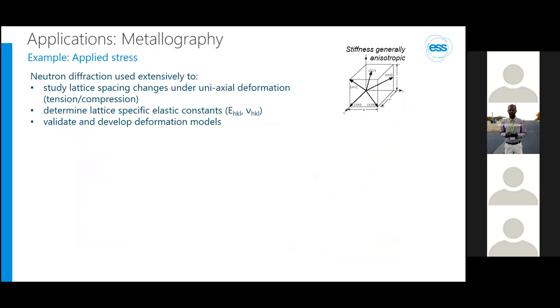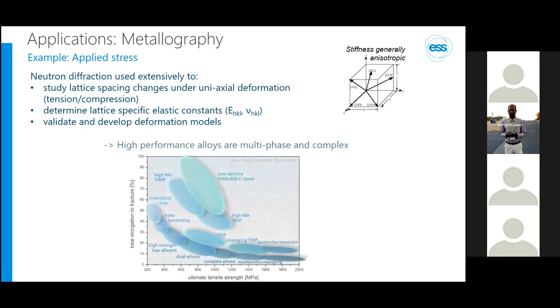One can not only study residual stress, but also applied stress, of course. And what is important here, since metallic alloys often behave very anisotropically, neutron and X-ray diffraction is extensively used to determine lattice-specific elastic constants under tensile loading, for example, and with that to validate and develop deformation models. When we look at this graph here, especially modern alloys that have a good combination of strength and ductility often consist of multiple phases and are fairly complex systems.